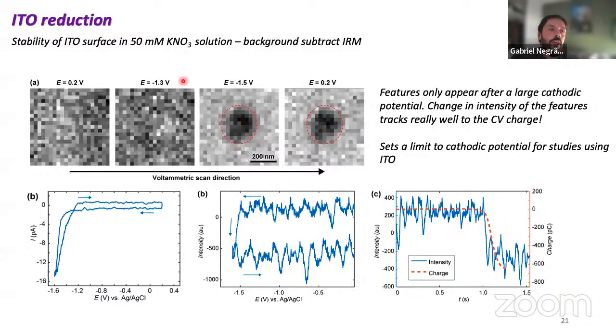But here I just have potassium nitrate. So what happened, we think, is that we're just reducing the ITO on the surface, making smaller parts of ITO. It's important to realize that, because this sets a potential limit window for the ITO where I can work. Besides that, it's going to be the substrate response. And because we saw the ITO is quite heterogeneous in the past examples, this limits the application quite a lot, because this behavior is not the same in all areas of the ITO. It changes a little bit across space. But it's quite nice that we can see a feature.